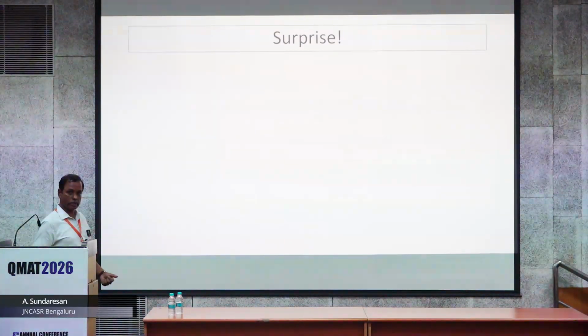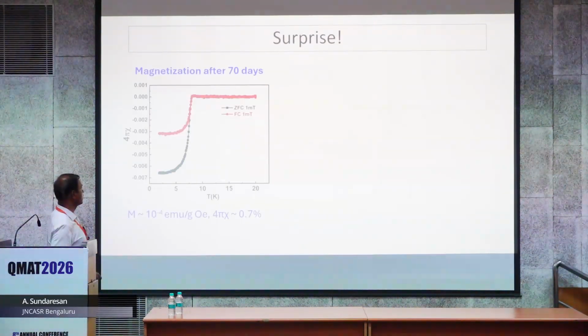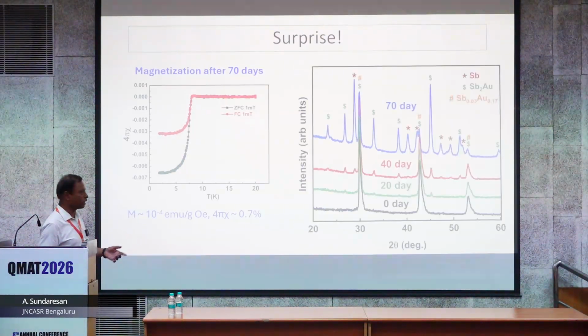But the surprising thing in this compound is that we wanted to do some measurement after some time. The student wanted to check the property, and he looked at the volume susceptibility, which was equal to 0.7%. That's what we first found, and then he looked at the X-ray, and what we found is it is completely decomposed within roughly 70 days.